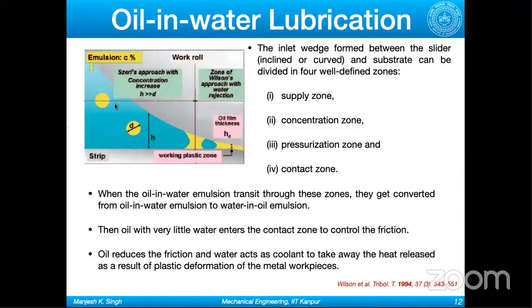As this emulsion is dragged into the contact zone, as I mentioned before, water has a very low pressure viscosity index. The water will simply squeeze out. As you move towards the contact, it changes from oil in water emulsion to water in oil emulsion, and when you reach the contact, you have only oil. So even in this case, it's only the oil which does the lubrication.